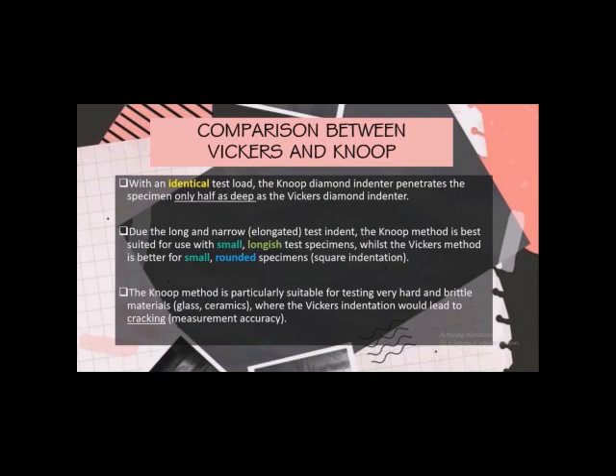And the third is the Knoop method is particularly suitable for testing very hard and brittle materials, for example glass and ceramics, where the Vickers indentation would lead this kind of material to crack. Why? Because the Vickers indentation is deeper than the Knoop indentation, so those kinds of materials will break easily if they use the Vickers method.